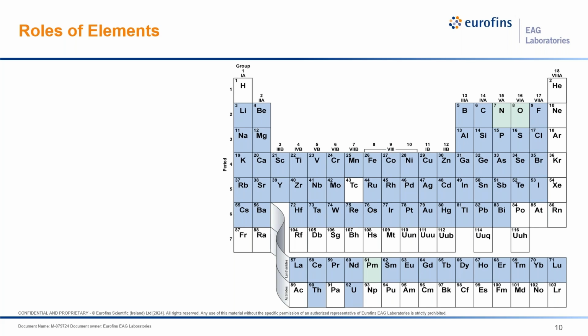Refractory metals serve as solution strengtheners in high temperature superalloys, but they're unwanted even at trace levels in electrolyte solutions. Sulfur, selenium, tellurium can form 2D semiconductors similar to graphene with weak forces between layers. However, these impurities in superalloys weaken the mechanical strength of these alloys at high temperature working conditions.